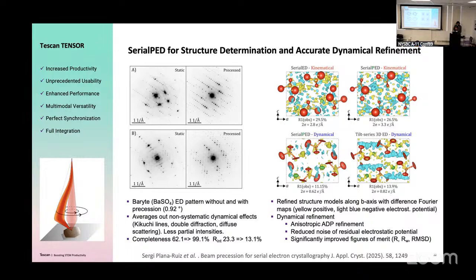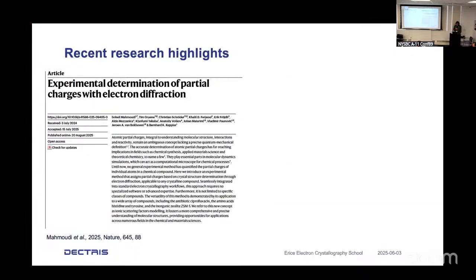As I said, you reduce the artifacts, and it significantly improves the R factors of the refinement and gives you better and more correct bond distances. So this is a very nice way to collect your data. Tim was very modest. He didn't mention his latest Nature paper.